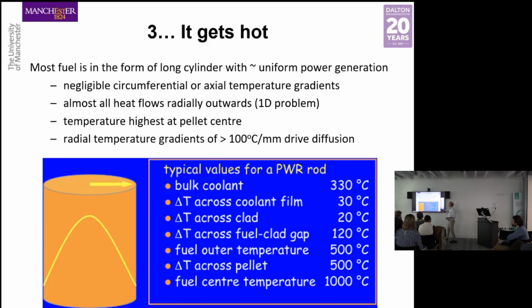A pellet is around about 4.5 millimeters in radius. The temperature difference between the outside and the inside is very large, roughly 500 degrees C between the center and the surface. So we have temperature gradients of over 100 degrees C per millimeter, and they're driving events like diffusion very, very significantly. In terms of a thermal analysis of the problem, thank goodness it's only essentially a 1D problem. Heat travels radially. It really doesn't travel circumferentially, and it really doesn't travel axial at all. So essentially it's a one-dimensional problem, but it's still a major problem, still some major thermal gradients going on in there.